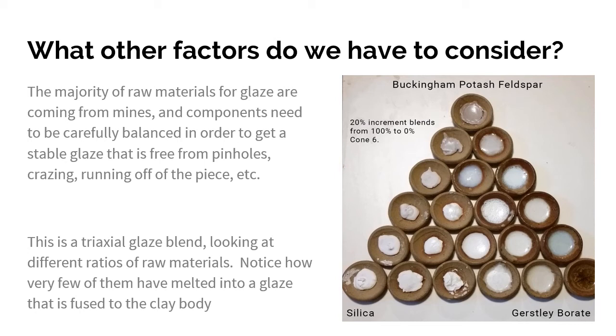And what you see in different pieces of this triangle is that some of them look nice and glaze-like, and then some of them are just lumps that they might not even necessarily melt. If they do melt, they don't necessarily fuse to the piece. I had an instructor who brought one of these into class, and half of the pieces were just hot glued into the cups because they didn't fuse at all to the clay body underneath and would just fall off.